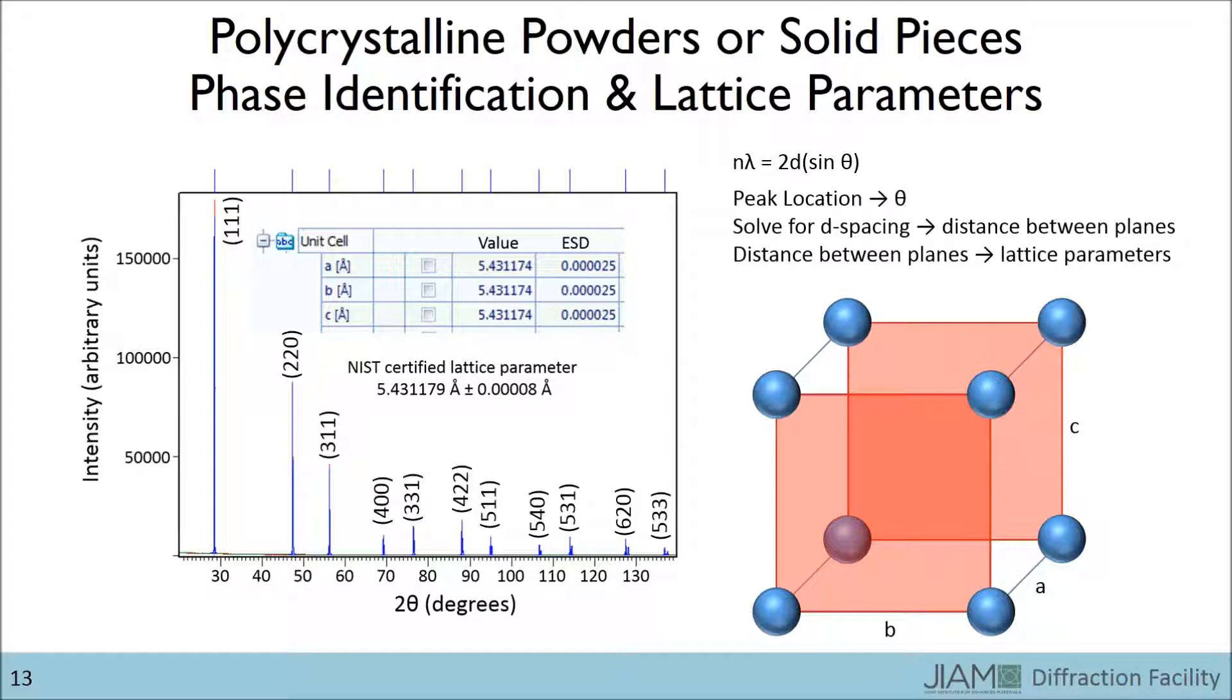Granted, this is an ideal reference material, so your experience may not be as fast, but the process is quite straightforward. If your material is a solid solution, utilizing Vegard's law along with the lattice parameters of the pure constituents and your sample could help you determine the composition of your sample.